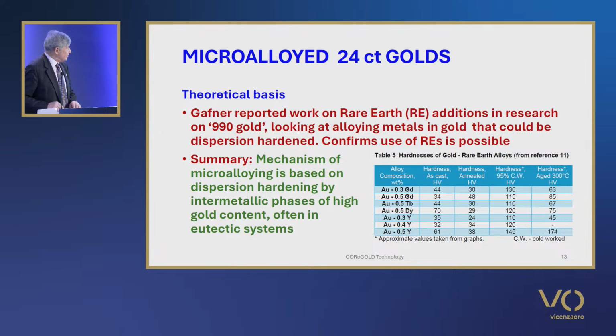So to summarise, the mechanism of hardening by microalloying would appear to be based on some form of dispersion or precipitation hardening by intermetallic phases of high gold content in alloy systems that form eutectics at high gold contents, and where the microalloying addition has little solid solubility in gold.